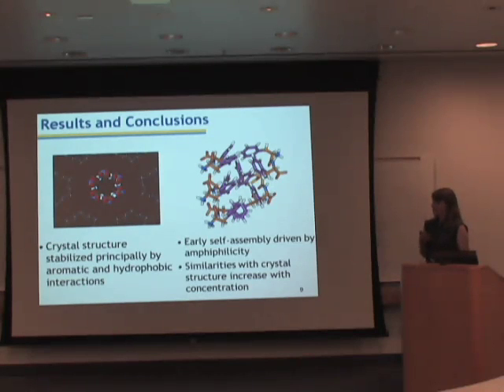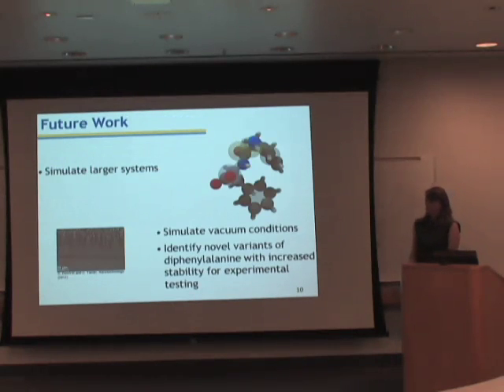Very importantly, we also learned that this hexagonal pore-like structure seen in the crystal structure is actually not the first structural motif we see when 6 of these peptides come together. Rather, hydrophobic interactions drive the earliest formation of 6-membered oligomers. Additionally, we find that as we increase the local concentration of the peptide, we see similarities with the crystal structure increasing. In future, we'd like to simulate larger systems to observe larger scale self-assembly.